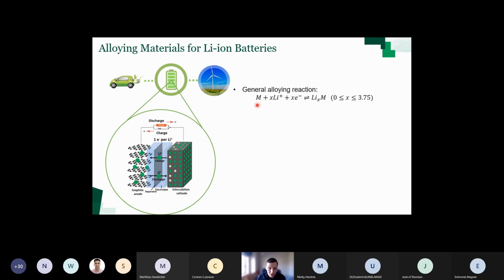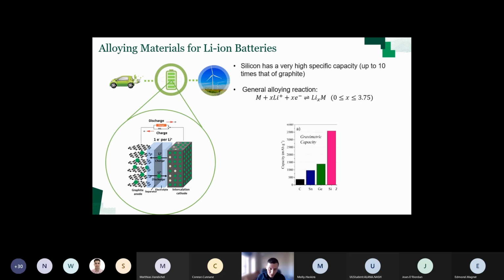Okay, so if you look at the alloying reaction here, if we take silicon to be the example, silicon will react with lithium ions plus electrons to form a lithium silicon alloy, and each silicon atom can accommodate up to 3.75 lithium ions at room temperature. So that's a considerable amount more than what carbon can. If you remember carbon, 6 carbons to 1 lithium. Here you have 3.75 lithiums to 1 silicon.